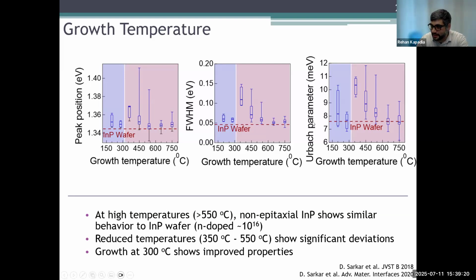And that's exactly what we saw here: at higher temperatures, we got something similar to the indium phosphide wafer, and then at lower temperatures it went up, then dropped back down, and if you went to too low of a temperature, then it just got ridiculous as well, because you're at such a low temperature that you're not getting the growth that you think you're getting. So what we found is that there's this interesting window on the order of about 300 C where you can start to get good quality material. And so that was for indium phosphide.